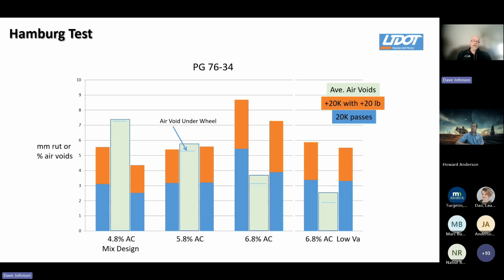The other thing that we want to point out is the air voids. So you can see we said it was multiple asphalt contents. They are showing here the results at 1% increments starting at 4.8% up to the 6.8 peak. And notice that the air voids underneath the wheel went from a little above 7% at that lower asphalt content all the way down to the lowest value in the far right of about 2% underneath the wheel on the 6.8 low air void count.